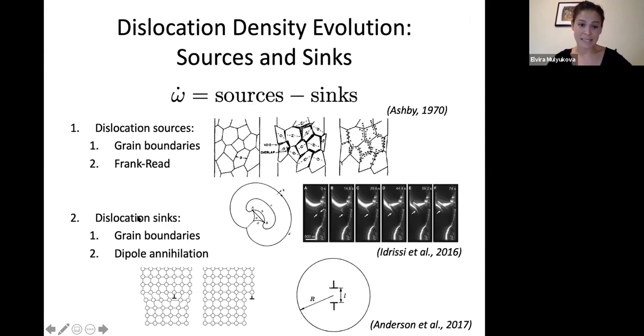For the dislocation sinks, we have grain boundaries. Most simply imagined, as a dislocation moves through a grain, by the time it reaches the grain boundary it's basically absorbed there, and its job in accumulating strain is done. So that is one way to annihilate a dislocation. Another dominant and significant contribution to recovery processes is what's known as dipole annihilation.